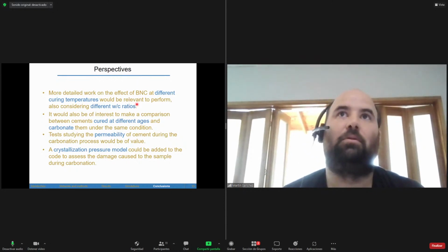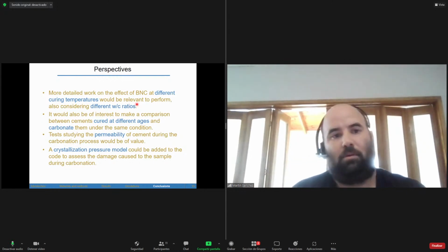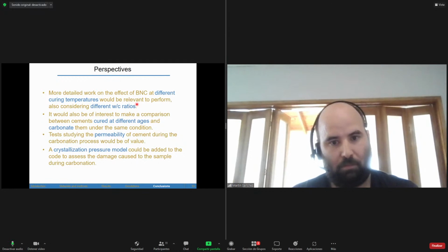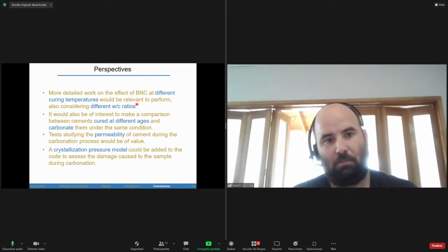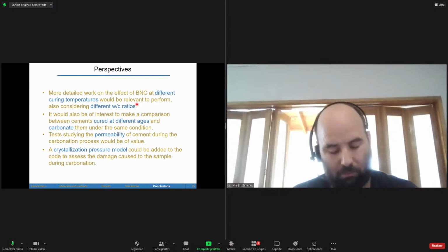I think the main problem in this case is going to be viscosity. I mean, we need to standardize the cement paste in order to have some similar thickening time and consistency to the one that we are using right now, because actually we first need to have a good distribution of bacterial nanocellulose on cement in order to make the additive be homogeneous, and that the amount of bacterial nanocellulose that we use and superplasticizer and any other additive that we use should be similar to the ones that we are using now. I mean, having a large viscosity may have problems of workability.